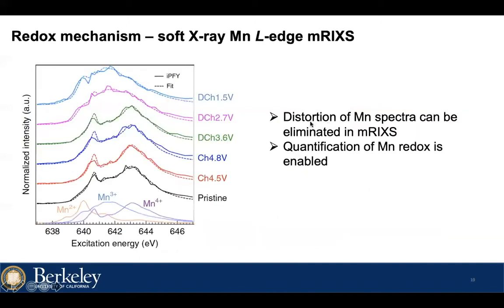And to quantify the manganese valence at each state of charge upon cycling, we performed the soft X-ray mRIXS on manganese L edge. This is a technique pretty similar to the soft XAS, but it can get rid of the edge distortion, so the quantification of the manganese valence is more accurate. By fitting the spectra with manganese 2+, 3+, and 4+ standards, we can get the valence of the manganese at each state of charge. I will show these results later, but before that, I'm going to show the characterization